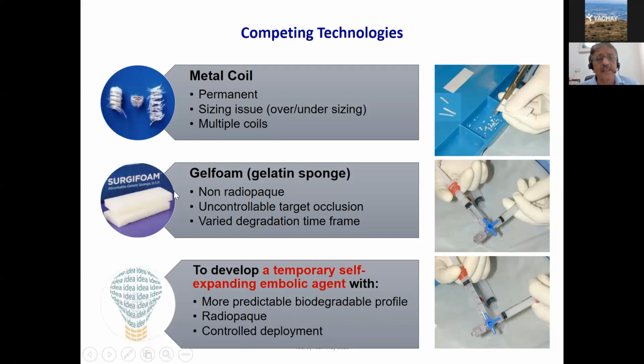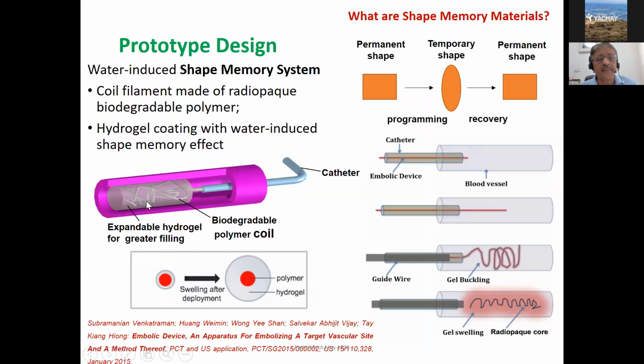Okay, I won't go into all the details of what we developed, but it involves the use of shape memory polymer. In this case, the polymer itself is made out of PLGA and can be made to have memory. So basically, the polymer itself is extruded as a monofilament, and then it is subjected to some procedures which allow it to have shape memory, which is the uncoiled configuration. Okay, and then it's coated with a hydrogel material, polyethylene glycol diacrylate, which is cross-linked, that can swell after introduction into the blood vessel.